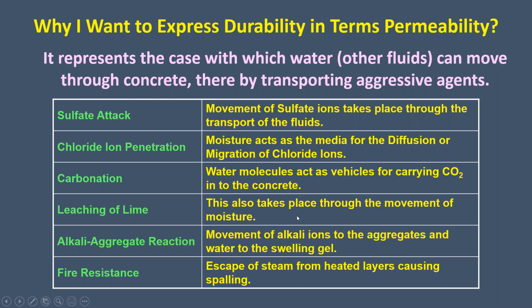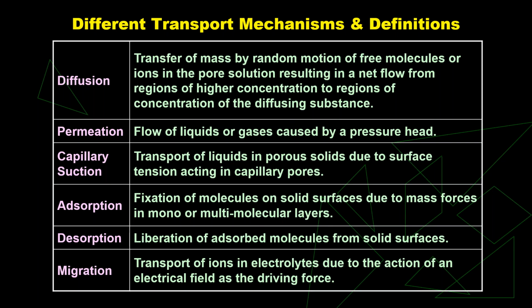If you consider the leaching of lime, this also takes place through the movement of moisture. Okay. And also if you consider the alkali aggregate reaction, movement of alkali ions to the aggregates and water leads to swelling. That means ASR, that also depends upon the permeability. If you consider fire resistance, escape of steam from the heated layers causes spalling. That means permeability is the root cause of all the durability problems. So we have to express our durability in terms of permeability. The other names of the mechanisms or definitions are diffusion, permeation, capillary suction, adsorption, desorption, migration, all those things. I'm not going into the definitions of these terms.